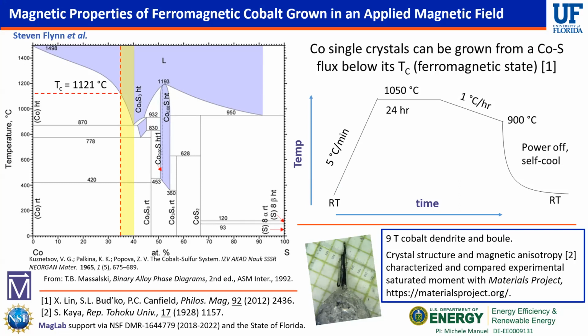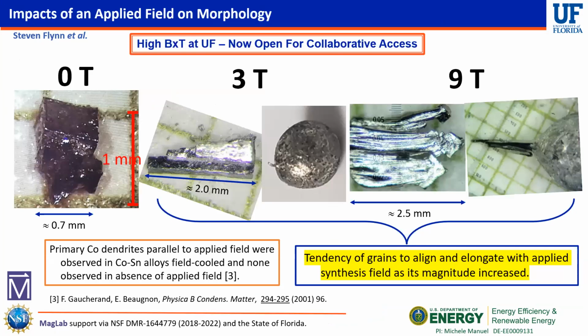So it lets you ask a weird question: what will happen if you do a crystal growth below the ordering temperature of the thing you're growing? We didn't know the answer to that, but we tried it. The heating schedule is shown here. It's nothing too special. And the result of that experiment is shown here. When you grow these crystals in zero field, they turn out as nice cubic looking things. And as you turn on the field, they elongate and eventually wind up as needle-like structures.